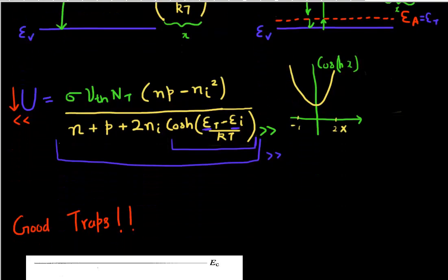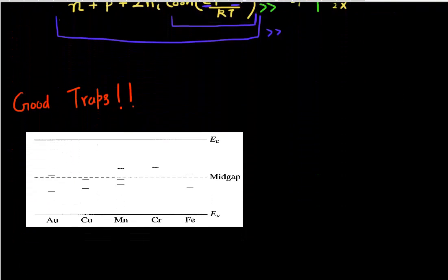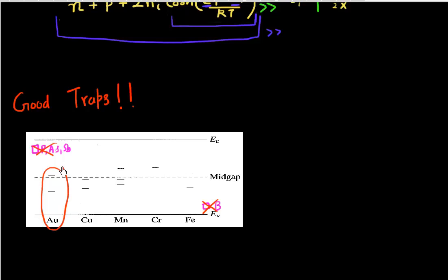That brings me to the question: what are good traps? If my energy level is close to the valence band or close to the conduction band — elements like phosphorus, arsenic, and antimony, which are good donors with energy levels very close to the conduction band, or boron, a good acceptor with energy levels close to the valence band — these are not very effective traps. The elements which are effective traps are ones whose energy level is very close to the middle of the band gap, such as copper and gold, which produce trap states close to the intrinsic energy level near mid band gap for semiconductors like silicon.